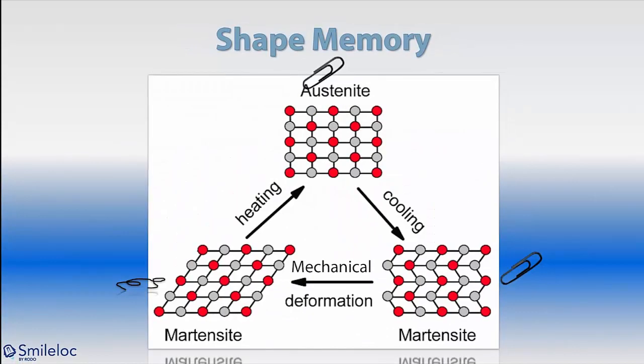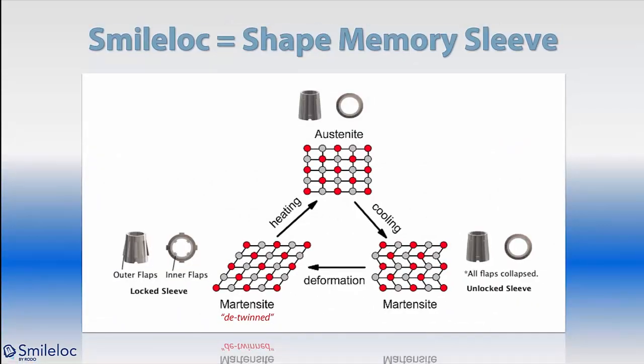Nickel titanium goes through phase changes. In its most stable condition, it is considered austenite. And you can see at the top of the screen, the lattice pattern is very even. When that metal is cooled, it becomes martensite. And while it's in the lattice pattern of martensite, it is able to be deformed, as you can see on the lower right-hand side, deforming into the lower left-hand side lattice pattern. Once it is deformed martensite, in order to bring it back to the austenite shape, it has to be heated.